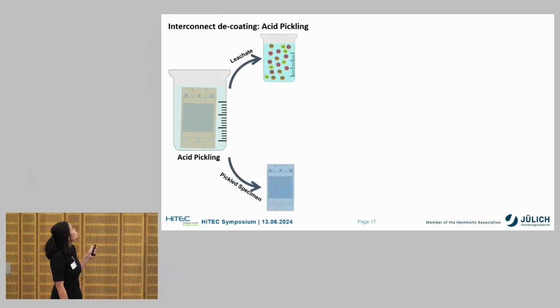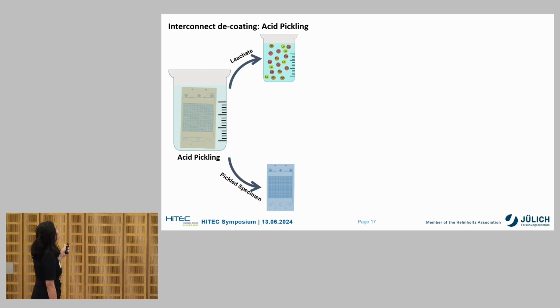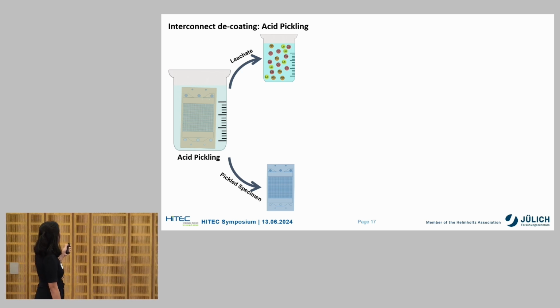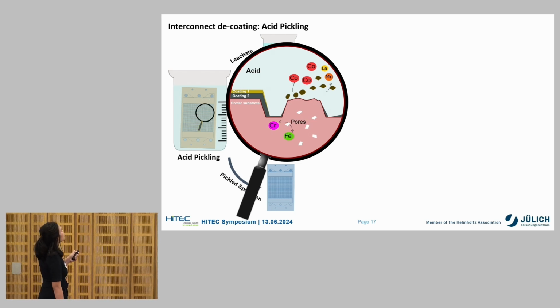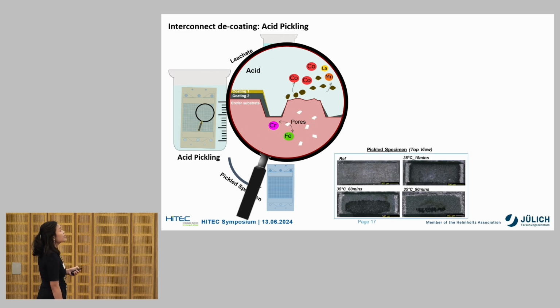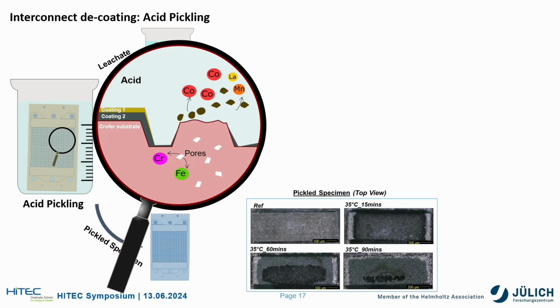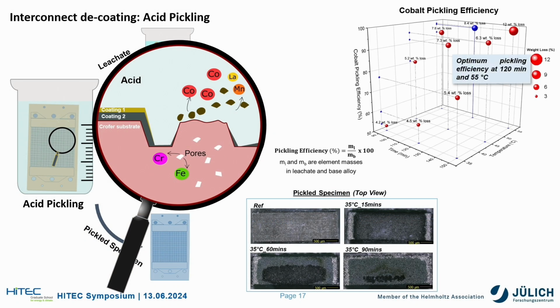As the name suggests, acid pickling involves submerging the entire sample in an acidic media, like this one. And the coating elements are presumed to go to the leachate, and the pickled specimen is sent for steel making. Taking a closer look on the surface of the sample during the pickling process, we presume that the coating elements get dissolved by the acid, and this is evident from this gradual removal of the coating layers as we increase the pickling duration. So we would try to obtain the optimum cobalt pickling efficiency by varying different parameters like time, temperature, solid to liquid ratio, and so on.